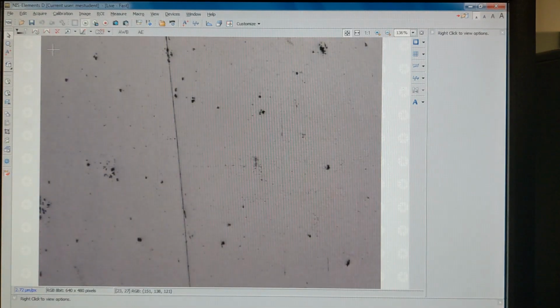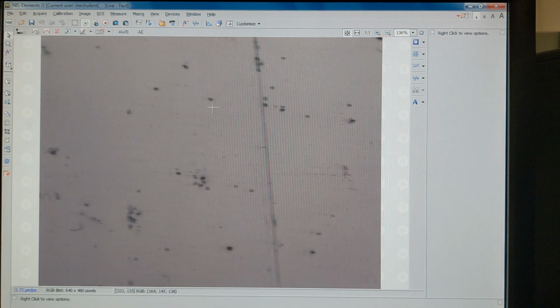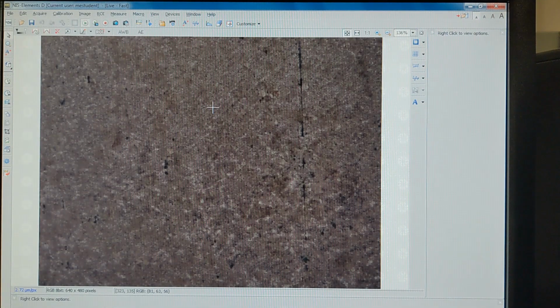It's a little blown out, so we focus. So this is our polished surface. As you can see, we still have a big scratch here. These little guys, these porosities, are just present on the interior of your sample. It's not always 100% uniform. You'll notice these on pretty much every microstructure sample you look at. So this is polished, polished, polished, but if we go to the side, you can actually see a transition. And here is our etched region. So you see it looks kind of grody.